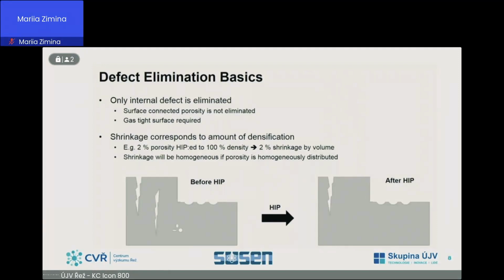HIPping will also eliminate internal defects. Any surface-connected porosity or any surface-connected feature will not be eliminated by the HIP process, since the pressure medium can penetrate this feature. The shrinkage in the process corresponds to the amount of densification we have. So, for example, if we have material with 2% porosity in the part, and we HIP it to 100% density, we will get 2% shrinkage by volume. If the porosity is homogeneously distributed in the material, the shrinkage will be homogeneous all over the part.